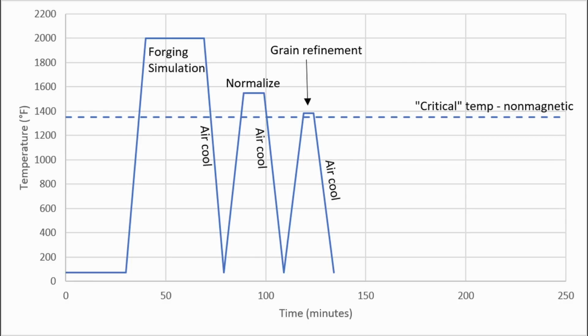And so what I do is a normal normalizing treatment, and then optionally you can add a grain refinement treatment where you heat it to non-magnetic and then air cool, and then nothing else. So just these 1 or 2 steps, normalize or normalize plus grain refinement. That's all you have to do. Then you heat to non-magnetic. Don't go any hotter.